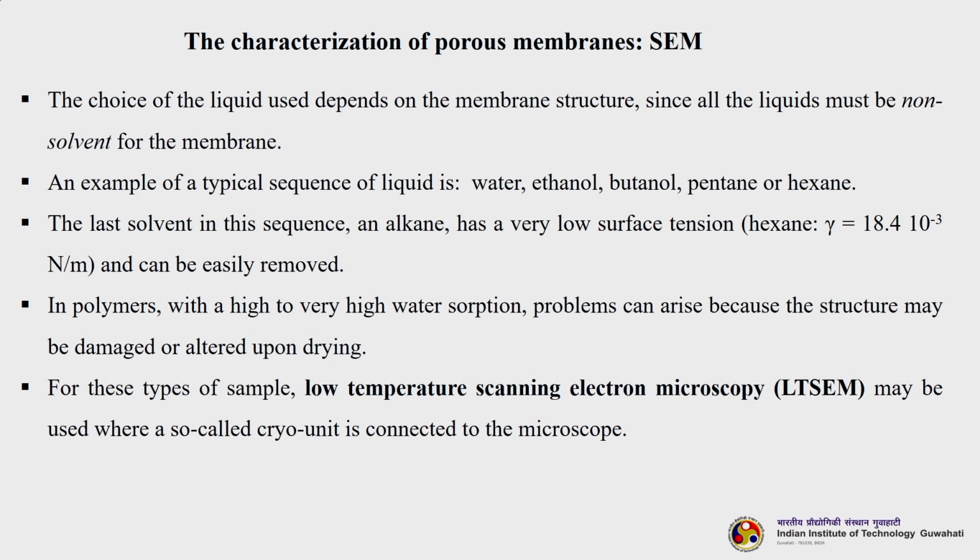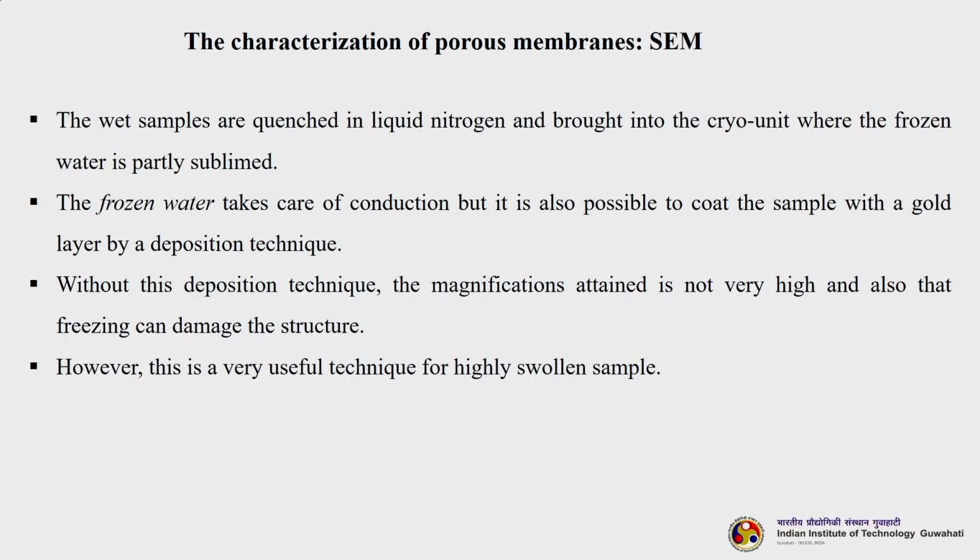So, for this type of sample, usually a low temperature scanning electron microscope, also known as LT-SEM, may be used. There is a cryo unit fitted to this microscope. Wet samples are quenched in liquid nitrogen and brought into the cryo unit, where the frozen water is partially sublimed.